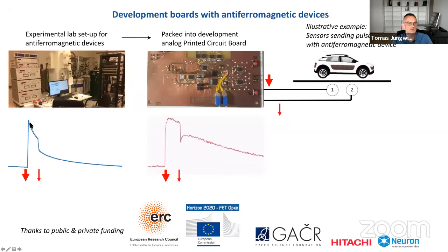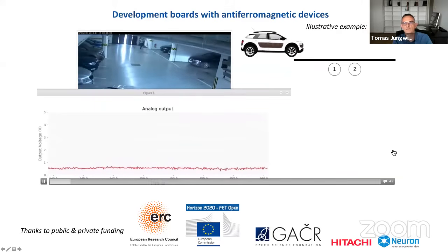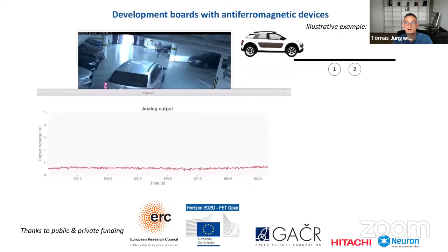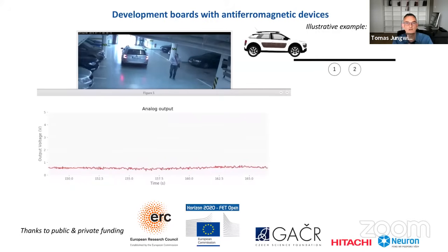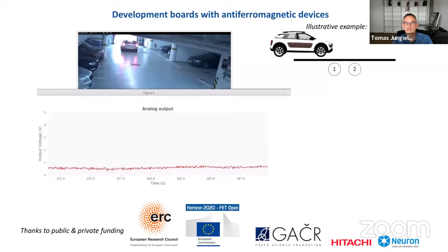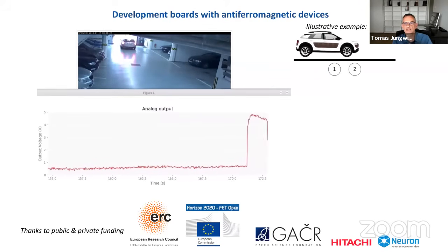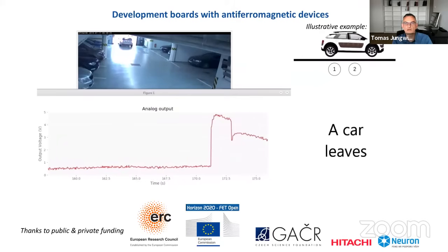And here you see what we measured in the lab on the same device, the falling edge. And here is the same response, but now detected using this very simple analog circuit board. Just to demonstrate that this board can work in ambient conditions, we can deliver two pulses, one stronger, one weaker, from two sensors which sense a moving vehicle. We will see in the last slide that if the vehicle is moving in one direction, and this is, by the way, taken in one of our real IoT development sites, the first sensor senses the stronger pulse, the second sensor senses the weaker pulse, and we record on this simple board